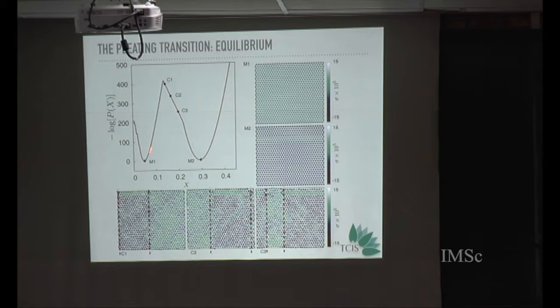So you can get these things by histogram reweighting in the usual way that you study first order transitions in a simulation. And you can see that it has this beautiful lever rule and an interface between two states, where this color here is the stress. So in one state, the stress is homogeneous, and in the other state, the stress is concentrated in this pleated region. So as soon as it forms a pleat, it eliminates stress from the body of the crystal and concentrates it on the pleat.